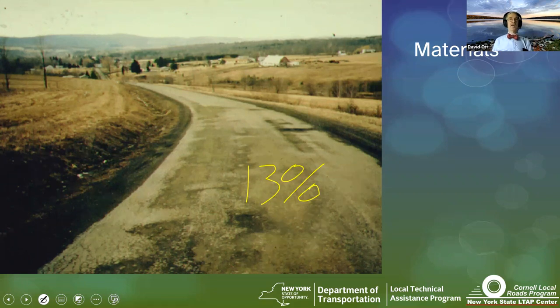It's not a chip seal problem. You could put the best chip seal in the world on it, but if it's got too much moisture in the base, that moisture builds up, it blows it apart. It's too soft when there's a lot of moisture available in the spring. It's a bit of a side hill. It's going to pop out in the roadway.